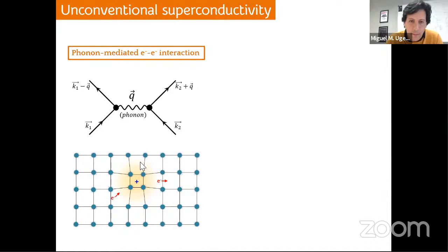Now, basically, one electron passes through a particular region in space, and the ion lattice gets distorted. So, in other words, this electron emits a phonon to the lattice, and basically this region becomes positively charged afterwards. And this region becomes an attractive region for a second electron that eventually absorbs this phonon. So this exchange of phonons is the conventional way to explain the formation of Cooper pairs in superconductors.